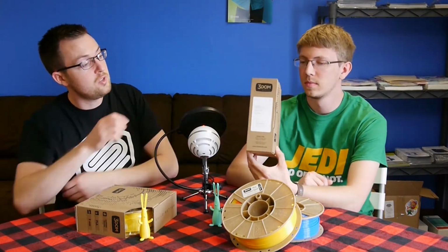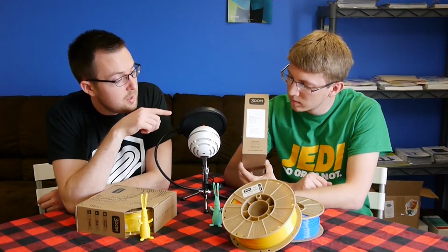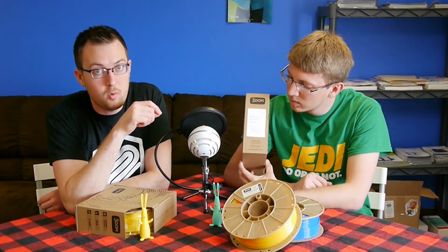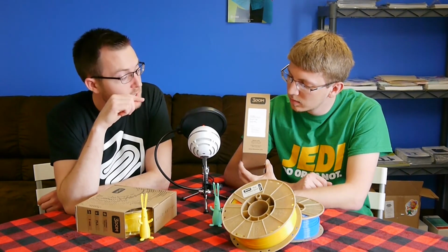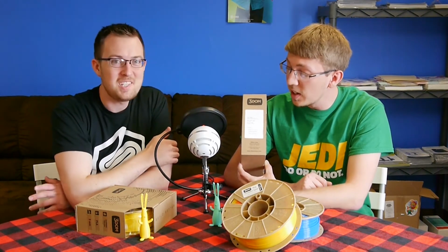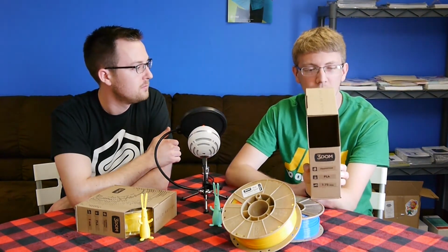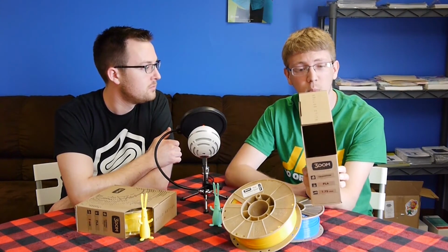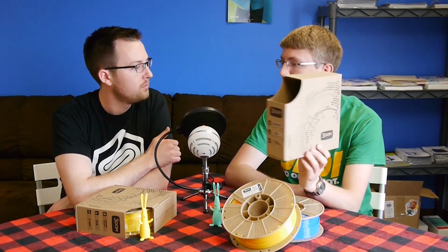And one thing to pay attention to is the upper and the lower limits on that strip chart. The upper limit is plus 0.05 millimeters. The lower limit is minus 0.05 millimeters. And so we get up really close to that diameter, and you can see that it varies very little. So it's very tight tolerances, very consistent to 1.75, because the mean diameter is 1.752. The ovality is 0.01. So we're very, very tight in our tolerances.